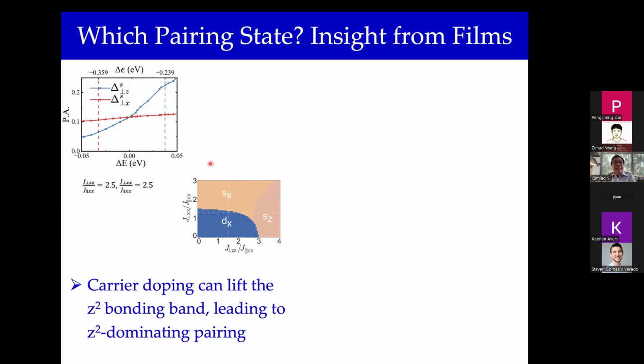So that makes the extended S-wave component, the pairing amplitude, stronger than the pairing amplitude of the x-square minus y-square states, which are always crossing the Fermi energy. Here we're analyzing the extended S-wave case. On the other hand, if the bonding 3dz-square orbitals sink sufficiently below the Fermi energy, the system, as far as pairing is concerned, cannot take advantage of the larger interplane J coupling between the z-square orbitals. So that gives a chance for the x-square minus y-square orbital contribution to the extended S-wave pairing to overtake the z-square contribution.